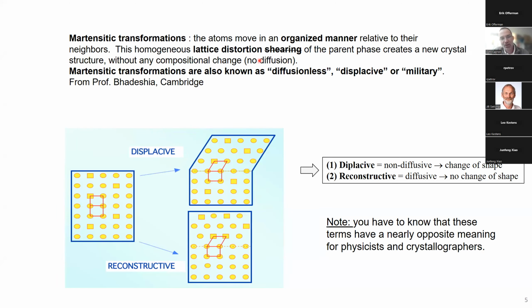There is no diffusion. So more or less, a martensitic transformation for us metallurgists means a diffusionless, displacive, or military transformation. I follow Professor Bhadeshia's definition for that. So it's displacive, non-diffusive, and there is a shape change. Here you have different kinds of atoms, round atoms or square atoms. After this lattice distortion, the atoms remain more or less at the same place, but the lattice was distorted, so it introduced a shape change.